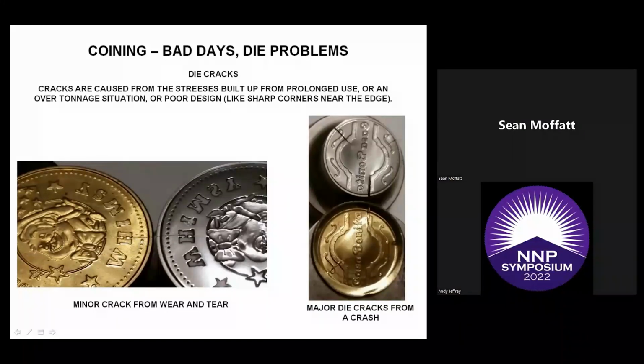We have a die crack shown right here. This is the die that that token is made with, and you can see the crack in the steel that goes off the edge and actually goes down the neck of the die away.